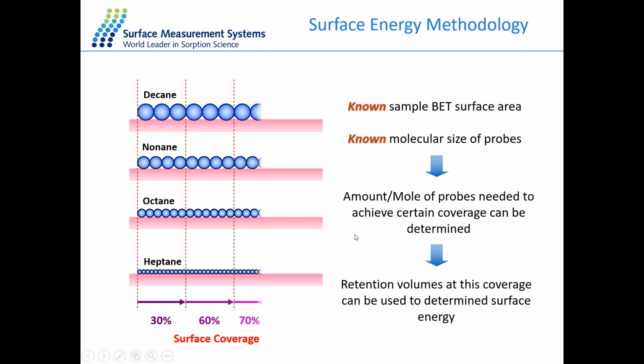So what we then go ahead and do is choose the amount of moles, or the amount of our probe, that we want to inject onto our surface to obtain a certain coverage of our surface. So once we choose what values to inject our probe molecules, we then carry out our experiment, and based on the interaction between the probe molecule and our material, we can obtain different retention volumes and analyze these peaks to understand the surface energy.